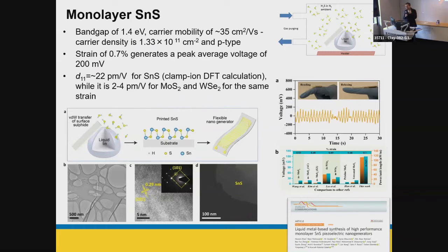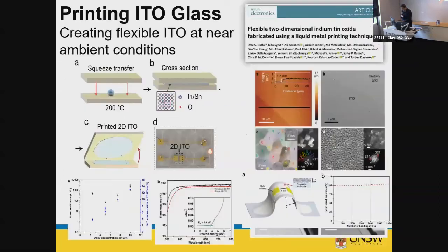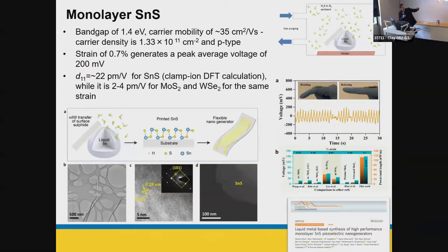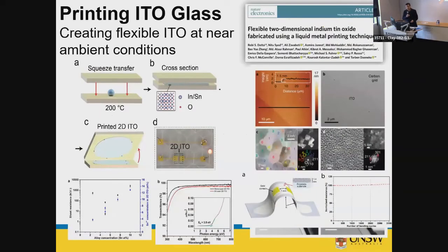Now, can we exfoliate tin sulfide? No. Although it's a layered material, it's a puckered two-dimensional material, exfoliation always causes the breakage somewhere. So directly making it like this allows the exfoliation of the two-dimensional material from the surface of liquid tin. And of course, we made this kind of devices that produce up to 200 millivolts and lots of current. As you see, it's a good piezoelectric material. It was a record at the time.